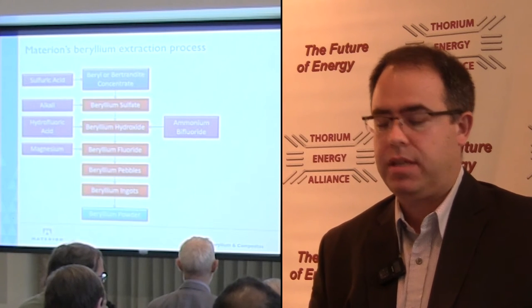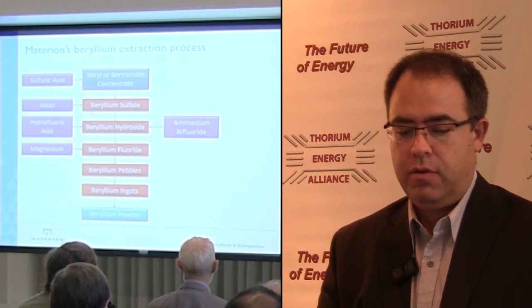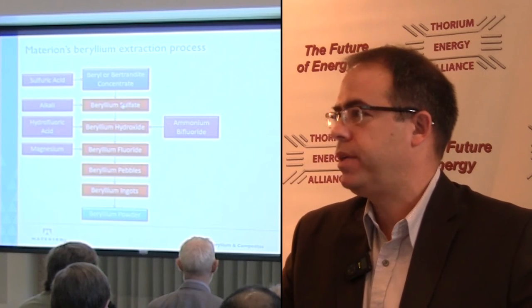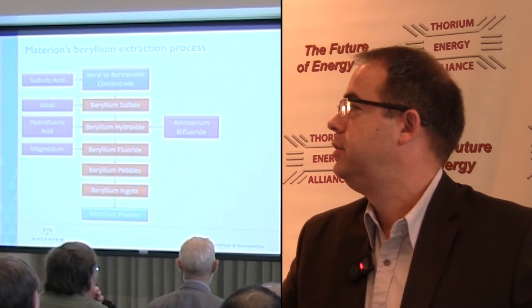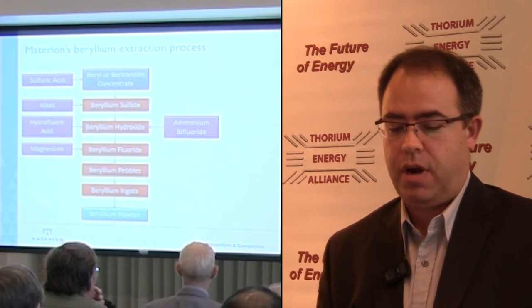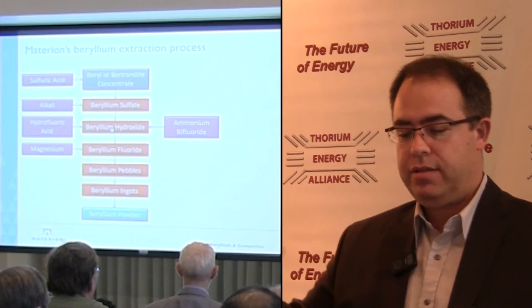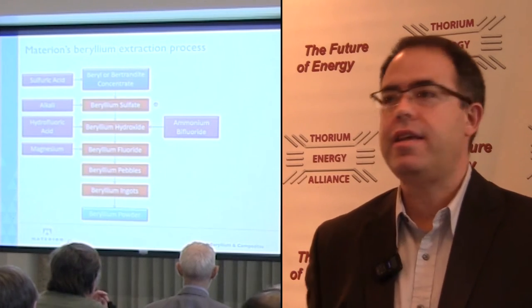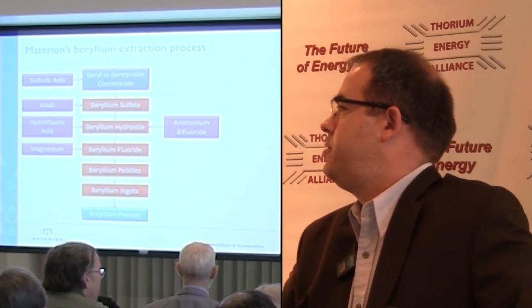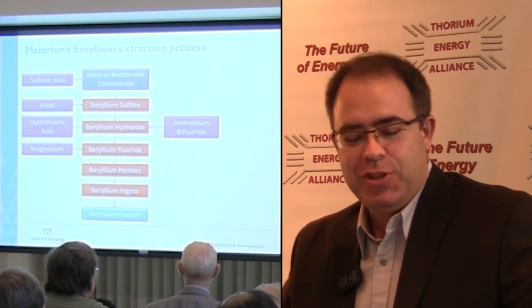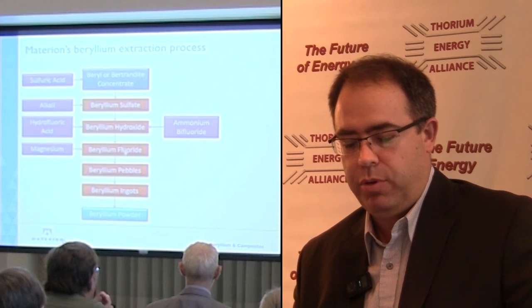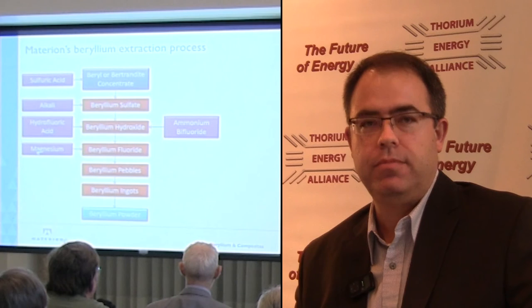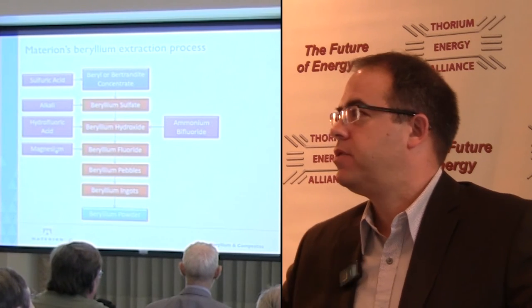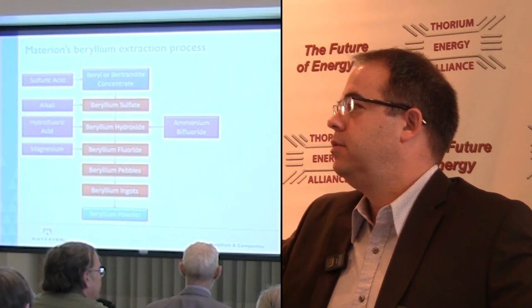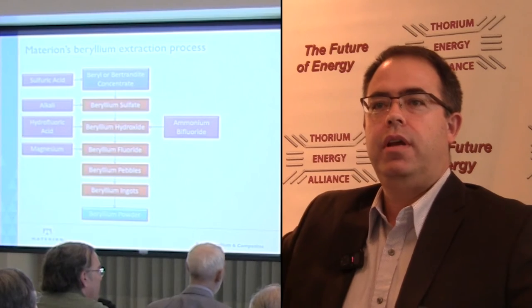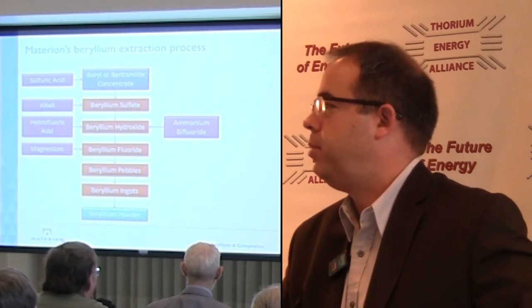So we take that. We basically add sulfuric acid, some pixie dust. We make beryllium sulfate, more pixie dust. Then we add an alkali in there. And what we do is we precipitate a beryllium hydroxide. That beryllium hydroxide, then we add ammonium bifluoride, and we add hydrofluoric acid, common stuff that you have under your kitchen sink, right? So we process that, and we end up at the end of the day with a beryllium fluoride, which we then do magnesium thermal reduction. We basically mix those two together at high temperature. The fluorine prefers to be with the magnesium and not the beryllium, and it's a displacement reaction, and you end up with these beryllium pebbles.